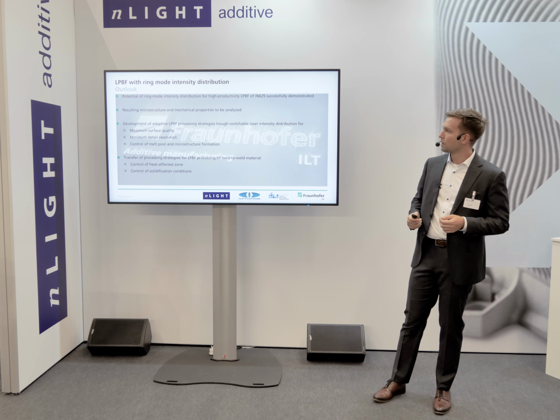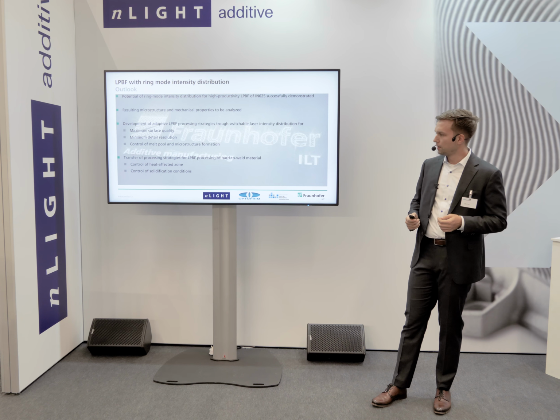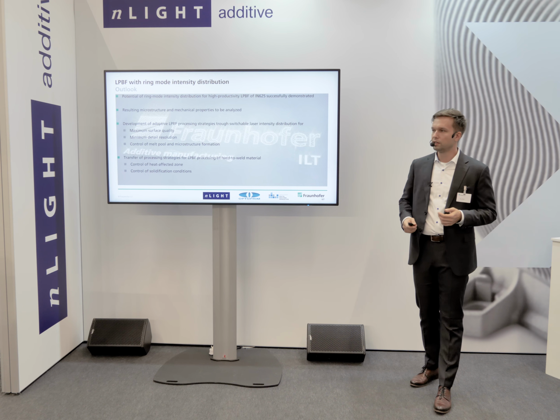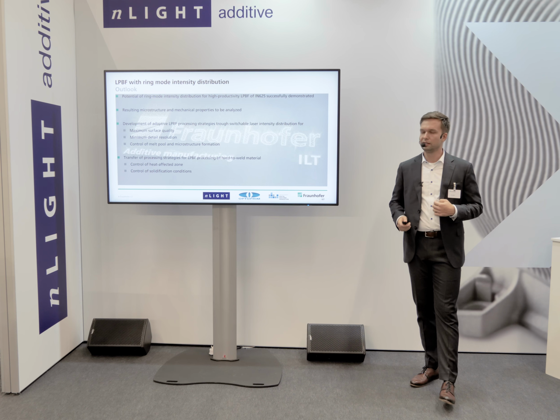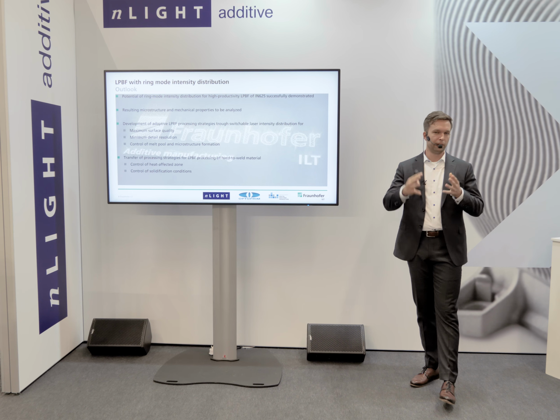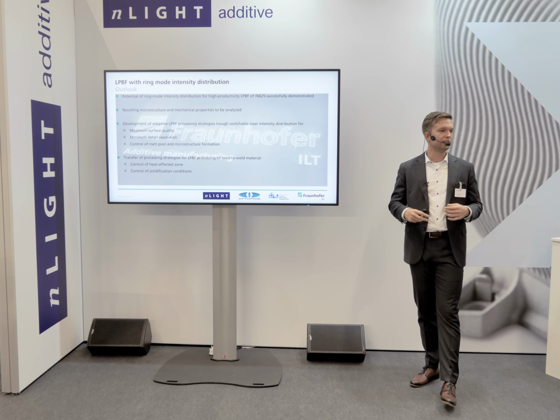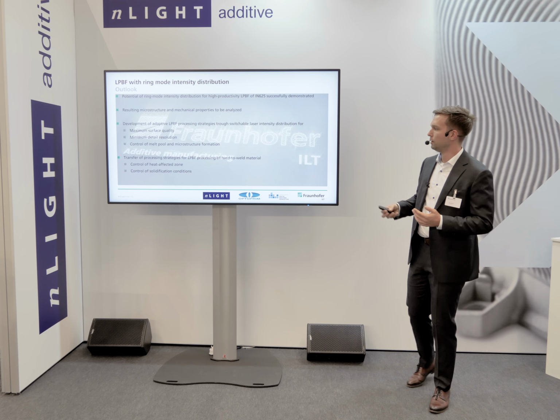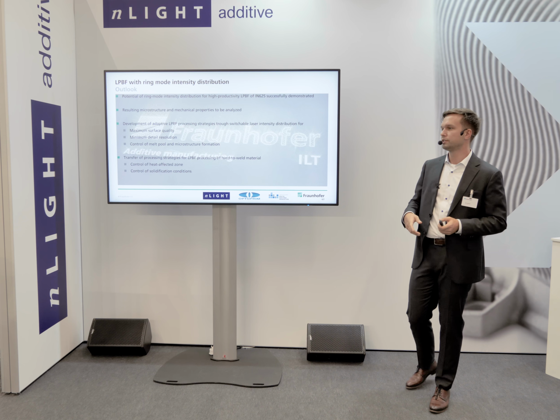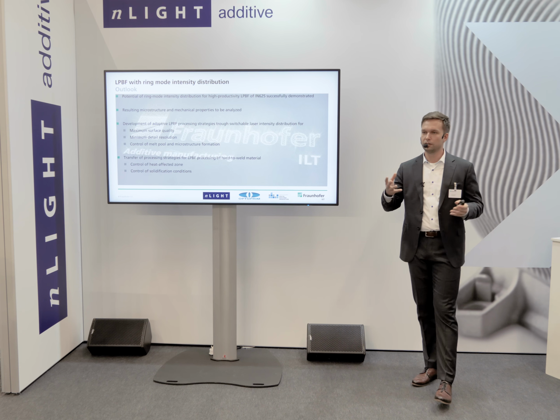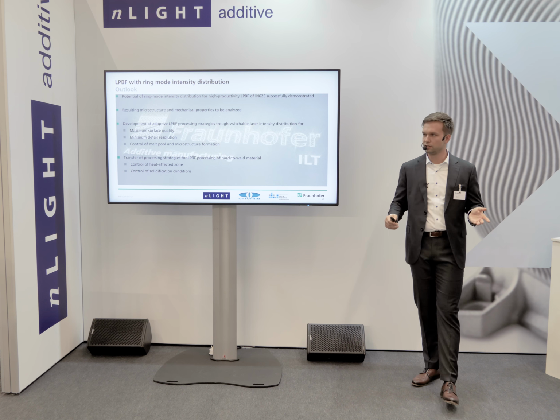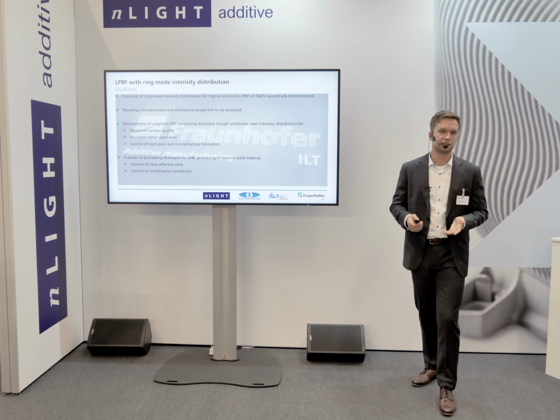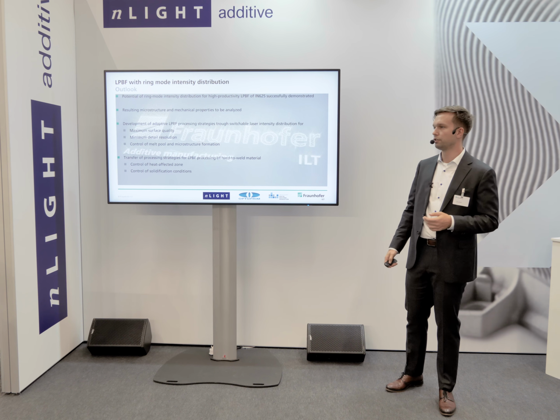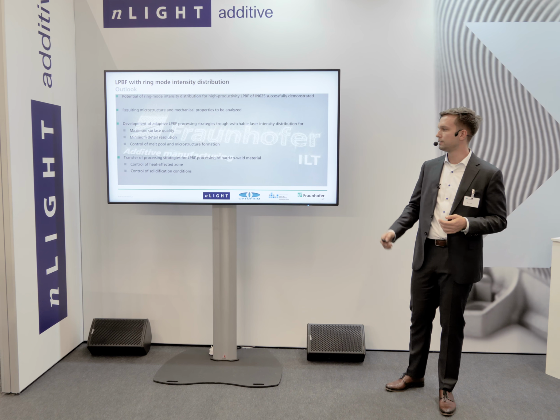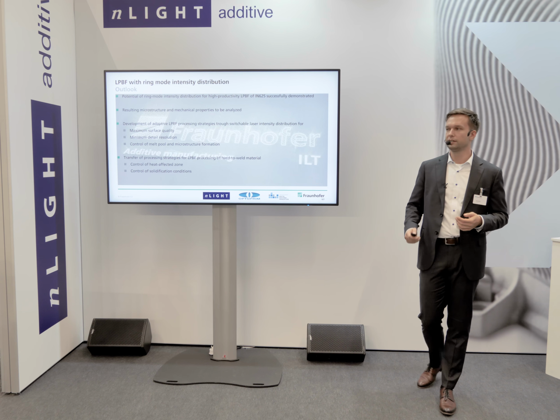And then, of course, we have some more insight into the, as I mentioned, the melt pool is flatter at the same energy input as for the Gaussian, which also is very interesting for processing of hard-to-weld materials because we can control microstructure evolution and also heat-affected zones, which may be beneficial for the future for these very critical materials and